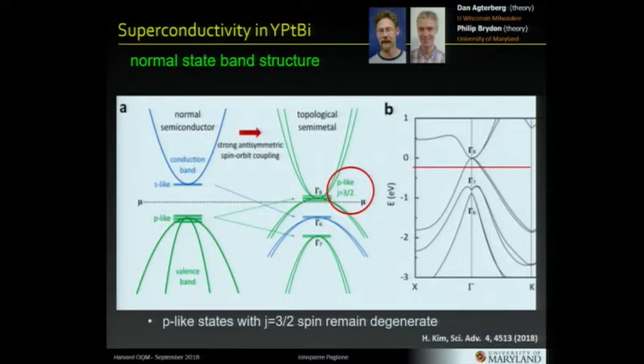And the interesting thing really is, and this is what Philip and Daniel pointed out to us, is that because this crystal has such high symmetry, in other words, there's no other bands around, it's cubic, it's very high symmetry, and the chemical potential is very close to this touching point, you actually retain this degeneracy of the J equals 3/2 states of the P-derived band of this gamma-8 band. And this immediately raised very interesting potential consequences for the pairing, because we know it's a superconductor experimentally. We know that at least the calculated band structure is quite interesting because you have this degenerate J equals 3/2 state. And then the question is, what is the pairing?